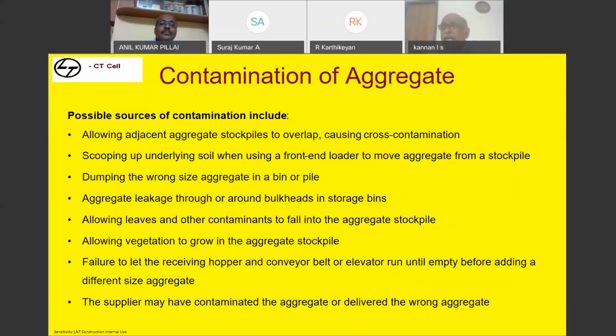Dumping wrong size aggregate in a bin. A 20 mm material may look slightly undersized, but you should not go and dump it in the 12 mm or 10 mm aggregate bin. If you are getting a perfect 20 mm aggregate, it may mislead. The same way, 10 mm aggregate should not go to a 20 mm bin. This can happen especially at night time, so we need to be very, very careful in dumping the material at night.